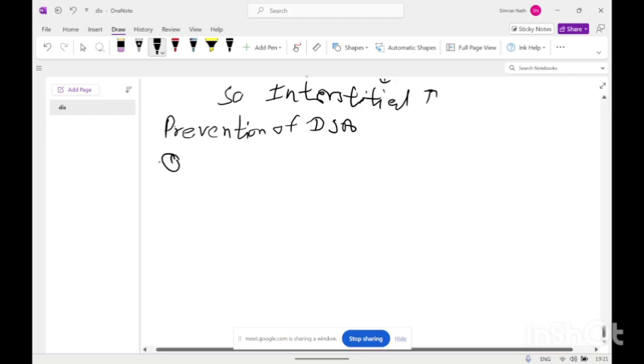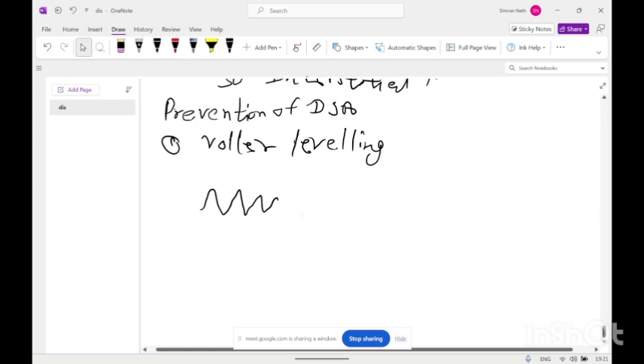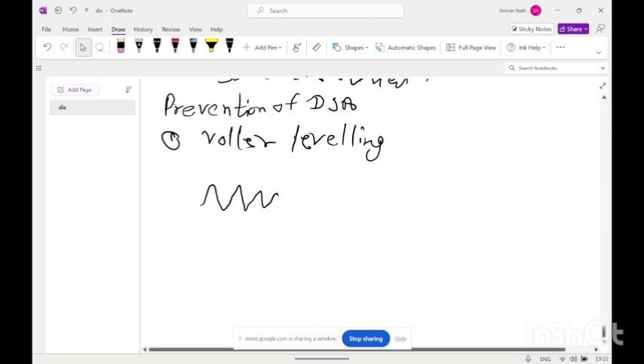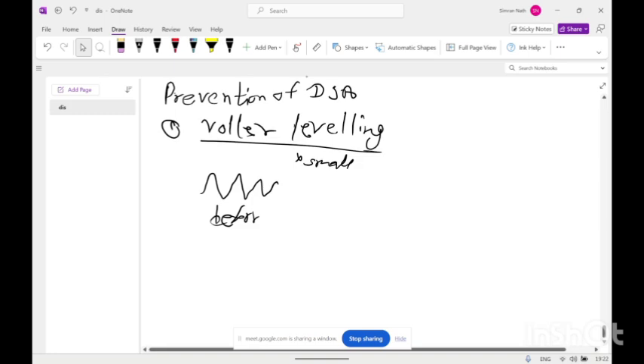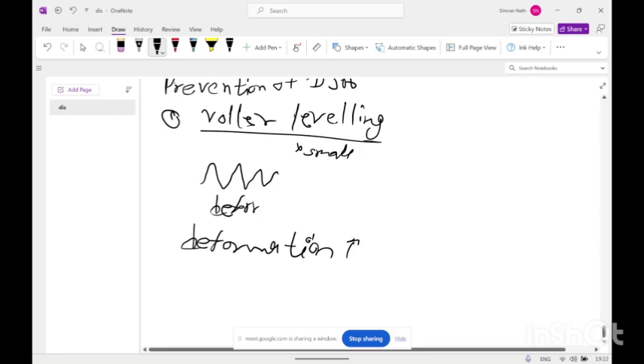So the first method is roller leveling, or temper rolling. In roller leveling, the sheet of aluminum alloy is fed to the small diameter rollers, and it will deform back and forth. That increases the deformation level and the dislocation concentration, so deformation will be higher and easier if it is pre-deformed.